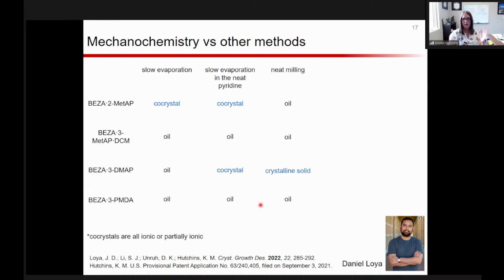So then we did our neat milling. We actually got oils with 3 of the 4. Interestingly, the 3-DMAP actually did give us a crystalline solid. And so that was a little bit unexpected compared to the rest. And then if we do that neat milling, then slow evaporation, that's where we get these 3 substituted pyridines, giving us co-crystals out really nicely, really reproducibly. And in the 3-PMDA, in this case, we isolated the 2-to-1 form. And I'll show you how we get the 1-to-1 in just a moment.